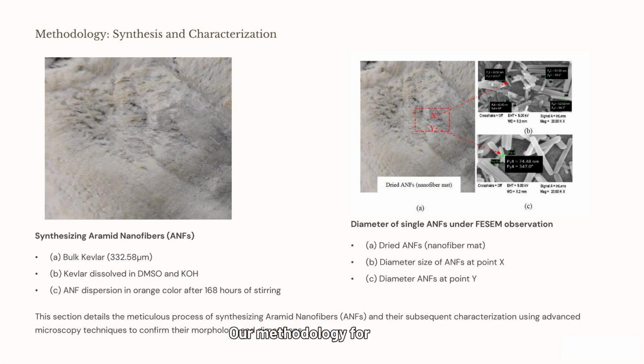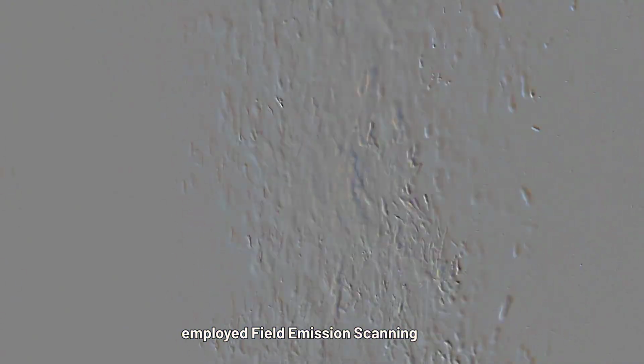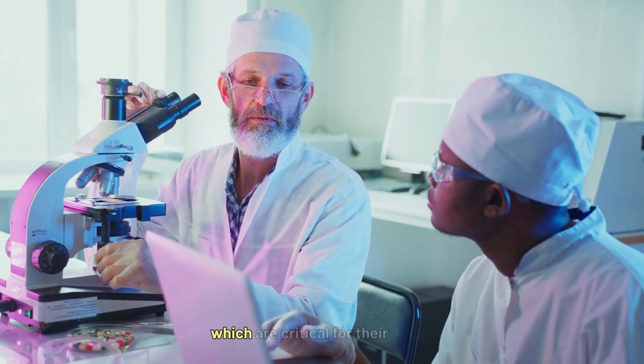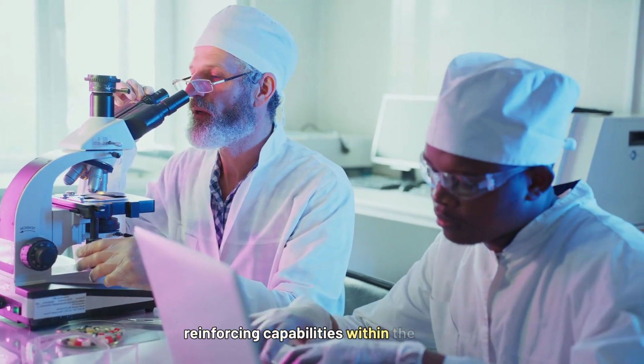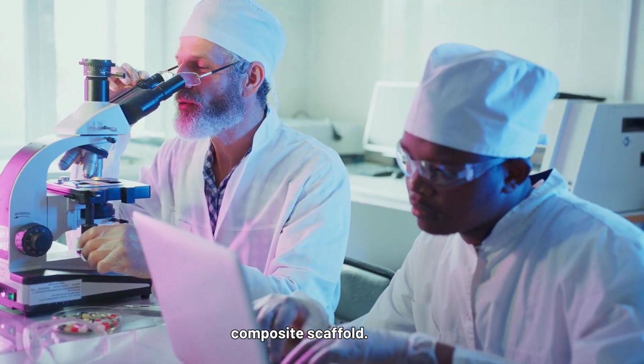Our methodology for synthesizing and characterizing aramid nanofibers involved a meticulous process, starting from bulk Kevlar to achieve a stable ANF dispersion. We employed field emission scanning electron microscopy to precisely measure the diameter of individual ANFs, confirming their nanoscale dimensions, which are critical for their reinforcing capabilities within the composite scaffold.